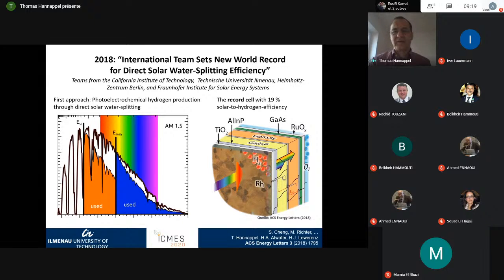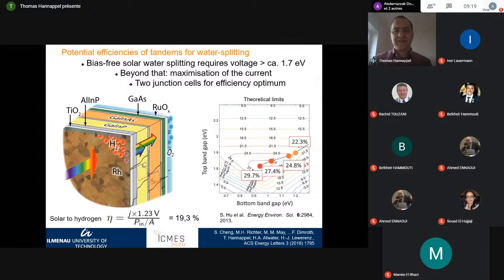And this piece, what you can see on the right hand side, of course, is too expensive, but the driver of the development, from my point of view, firstly is the efficiency, and secondly then the costs. I will get to costs later, but the point from my point of view is, if the device is not efficient, it does not make sense to use materials which are cheap, but which can never reach the target, and the target might be having efficiencies in the range of 15 to 20 or even higher percent. So yeah, these are the theoretical limits.